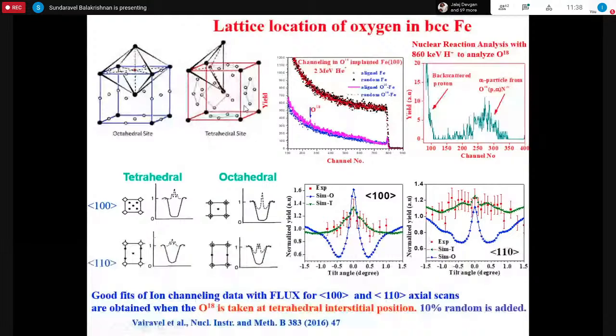And as such, depending upon whether it is sitting in an octahedral or tetrahedral position, this oxygen tilt angular curve will have different shapes. For example, for octahedral, along the 100 direction, we should get a curve something like this, and for tetrahedral it has to come something like this. In our case, whatever we observe is tetrahedral, and we get the shape like this. This shape we can simulate with the FLUX software, and we can exactly tell what it is. And for looking at this, the signal is from RBS from iron. Oxygen is not visible. For looking at oxygen, we have studied nuclear reaction analysis in situ, and this oxygen intensity of NRA is plotted here.